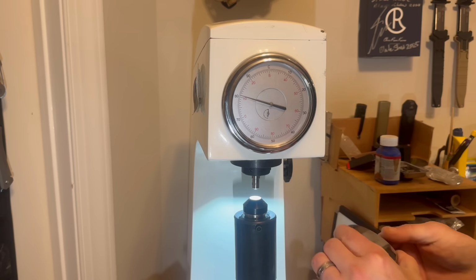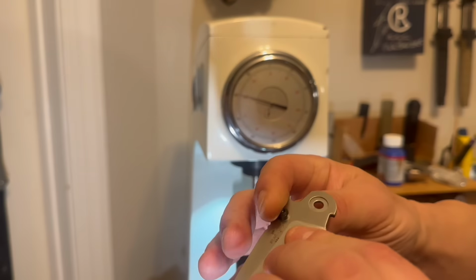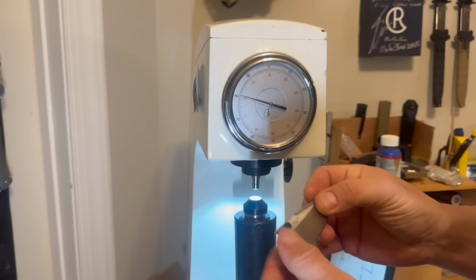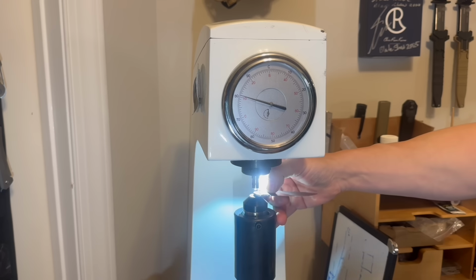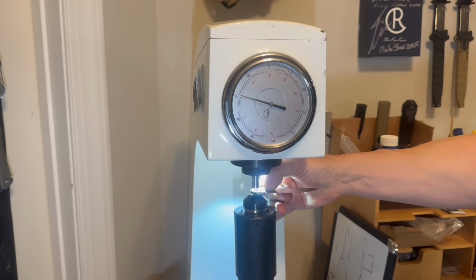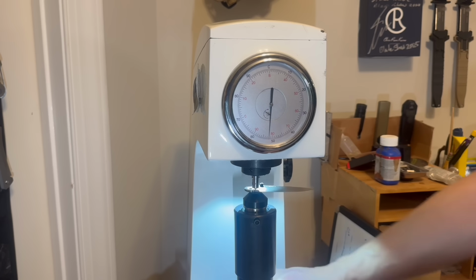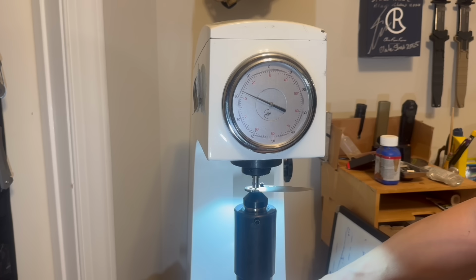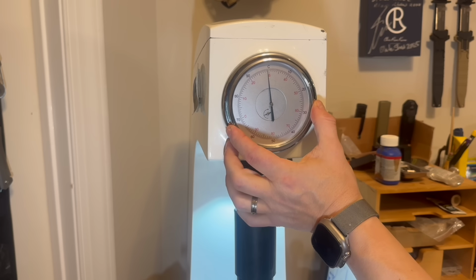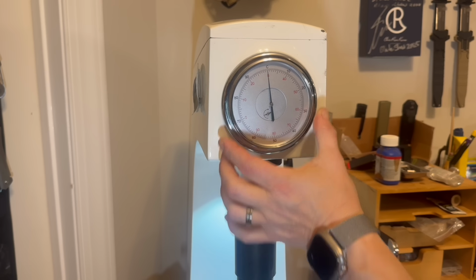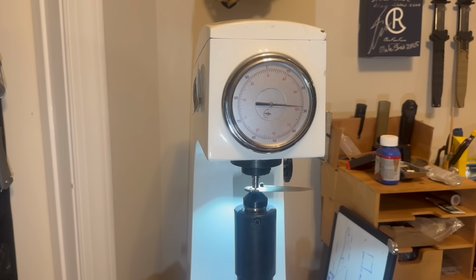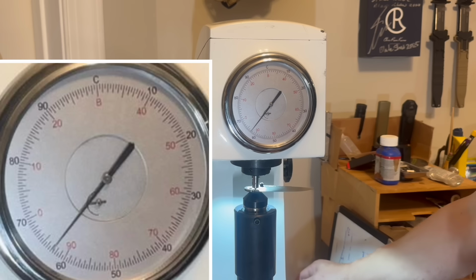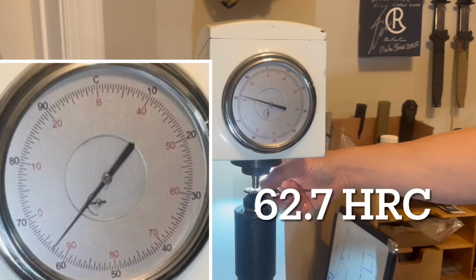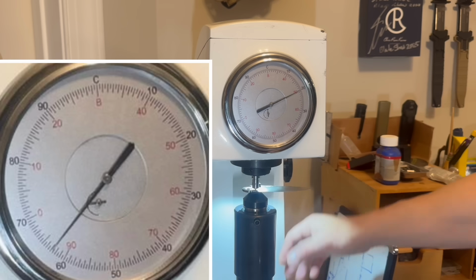And this segment is accelerated now for your time's sake, putting the uncoated blade on first. But the segment is fully uninterrupted, unedited, and continues, so that you see there are no shenanigans going on behind the scenes. I'm not editing anything in and out. For 14C28N stainless, the expected hardness range is 58 to 62 HRC. However, I've seen it pushed higher than that on very seldom occasions. What? I got 62.7 HRC.